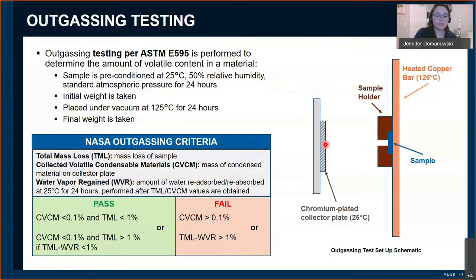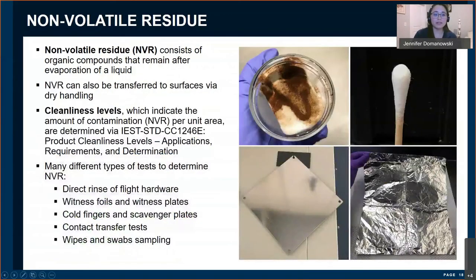So the type of chemical analysis that I do in my lab usually consists of analyzing non-volatile residue, or NVR. And typically the NVR that I analyze consists of organic compounds that remain after evaporation of a liquid. However, NVR can also be transferred to surfaces via dry handling. So this is what I was talking about with the bagging and the gloves. A lot of times bagging and gloves can have slip agents to help everything not stick together. There can be coatings on it. So all that type of stuff can be transferred to your spacecraft just by touching it. So that's a big concern.